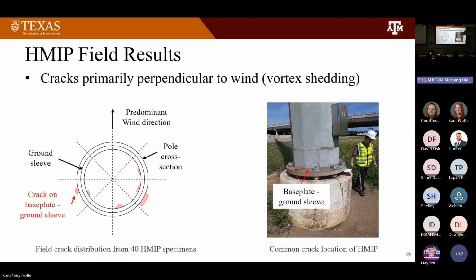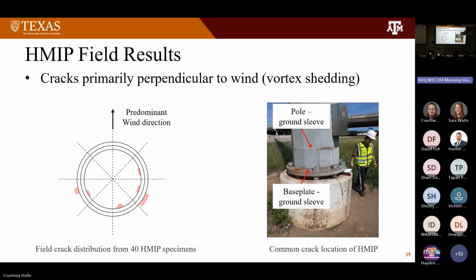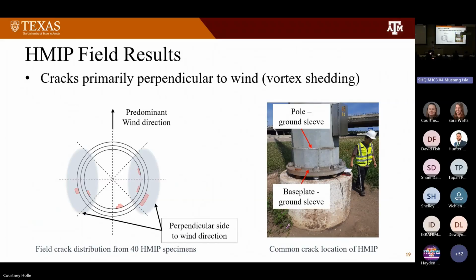And cracks located between the base plate and the ground sleeve were marked on the outside, and those between the pole and ground sleeve were marked inside. So overall, cracks tended to be located on the side perpendicular to the predominant wind direction, which supports the idea that vortex shedding is the primary reason for fatigue damage of HMIP.